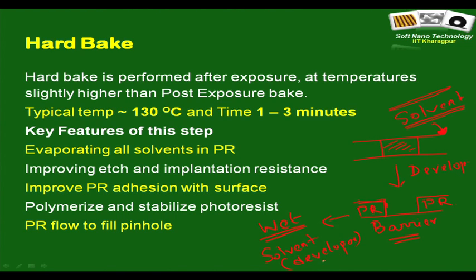The next stage after development is etching, to transfer the patterns from the photoresist to the barrier layer. The presence of solvent within the photoresist will interfere with the etching step and the chemicals used for etching. So it is important to eliminate the solvent, which is done by hard baking. This is interesting — you have different baking stages in photolithography: soft baking removes solvent after initial spin coating so it is not present during UV exposure; similarly, after development the photoresist again contains solvent that needs to be removed by hard baking.